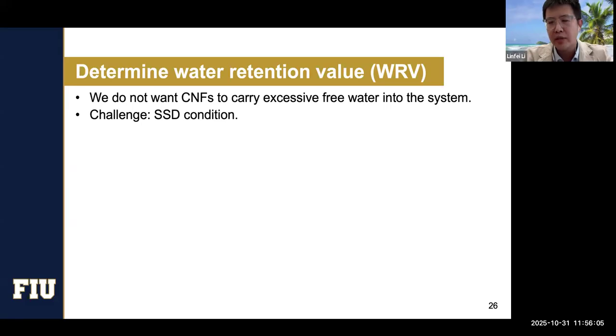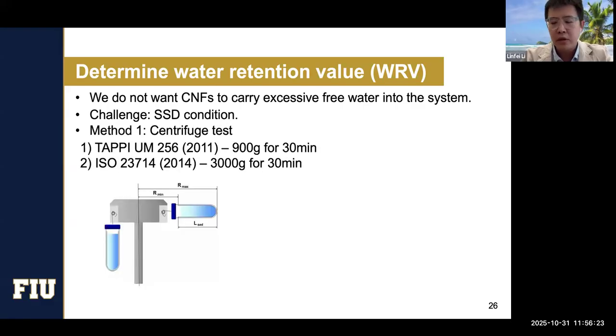For the lightweight aggregates, you can do ASTM standardized testing. For the superabsorbent polymer, you can also do the tea bag method. But for this material, there's no exact way to quantify the SSD condition. So here, my student and I spent a lot of effort trying to figure it out. It turns out we used two different methods. The first one, we used a centrifuge. For centrifuge, there are also two different standards which have been published. People claim that as SSD for cellulose nanofibril.